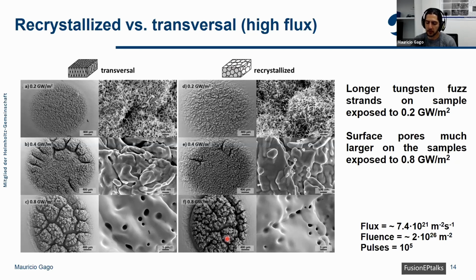So increasing the plasma flux and comparing it between high flux and low flux exposure is very important, because in ITER, the total fluence is expected to be several orders of magnitude larger than the ones with which we tested these samples. And this means that any effects brought by the exposure to plasma should be expected to be exacerbated during full DT operation, so deuterium-tritium operation, once the reactor is actually functioning at its full capacity. But we can already see that there are some differences between these two fluxes or fluences.